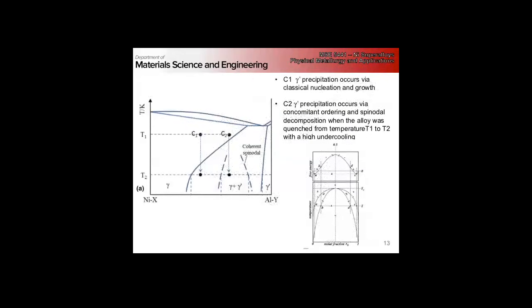So in spinodal decomposition, we come down to the inflection points on our free energy curve. I'm not going to test you on that, but just as a reminder of the mechanism behind spinodal decomposition - if we come down spinodally, we'll have gamma of this composition and gamma prime of this composition. Then we'll need long range aging time to separate completely into our equilibrium gamma and gamma prime.